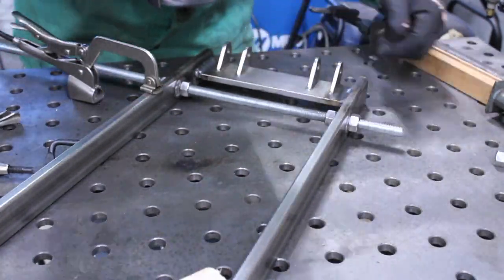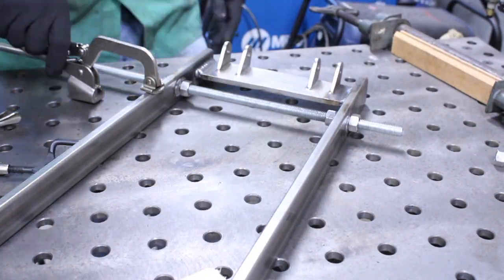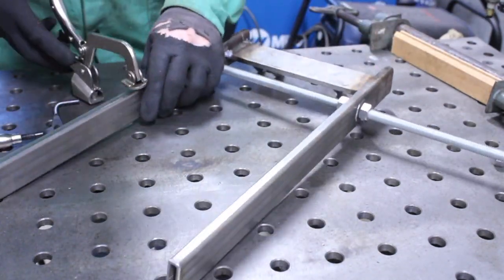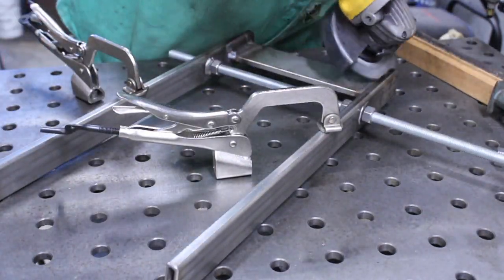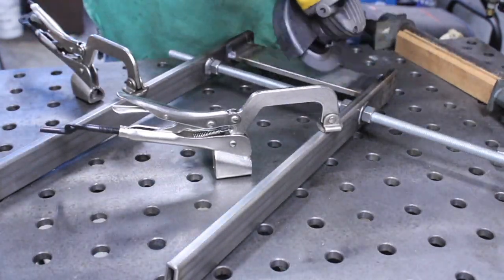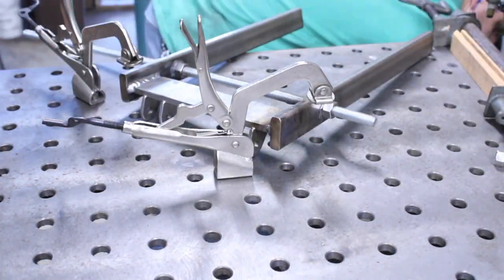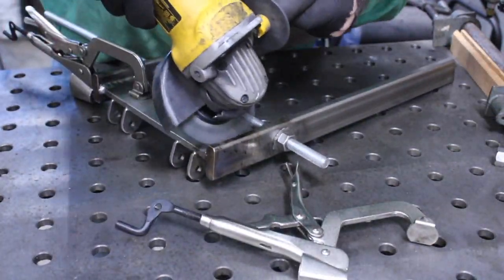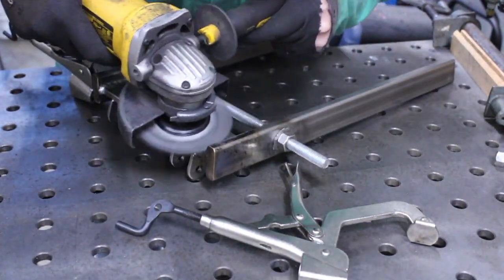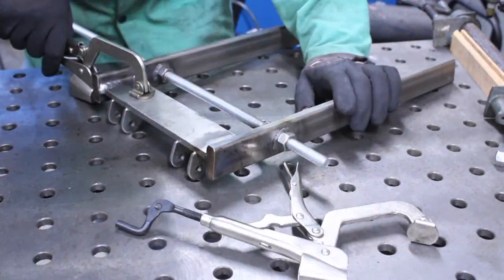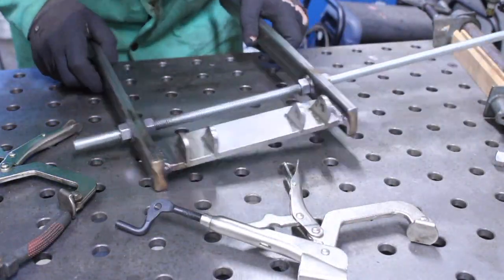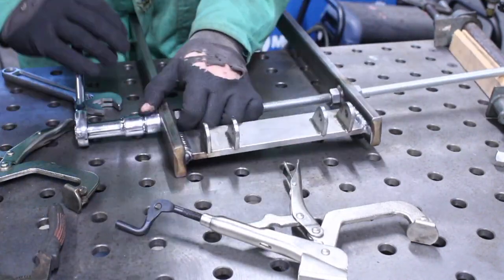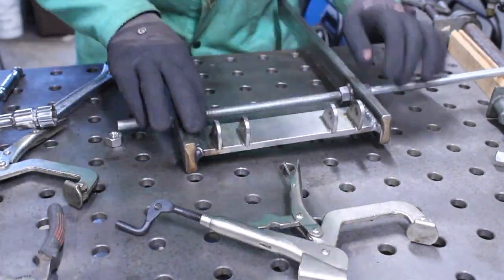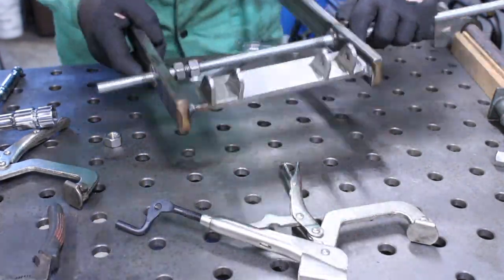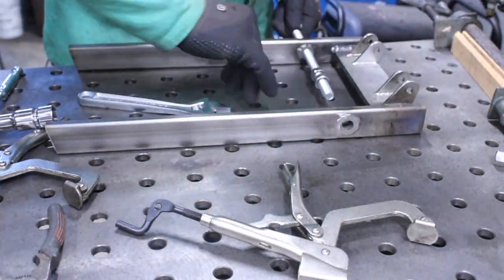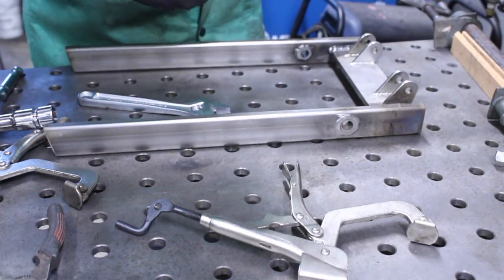As well, grinding carbon steel in proximity to stainless steel can result in similar issues. This is known as iron fallout contamination, and a great example of this is in the automotive detail industry, where on a car located in or near a city or even a train yard, you start to see rust spots on the paint that eventually work through that paint. Carbon steel dust suspended in the air can land on nearby stainless steel and lead to corrosion. This is why it's a good idea to keep carbon steel and stainless steel work areas separate, but that's not always possible for a lot of shop spaces.